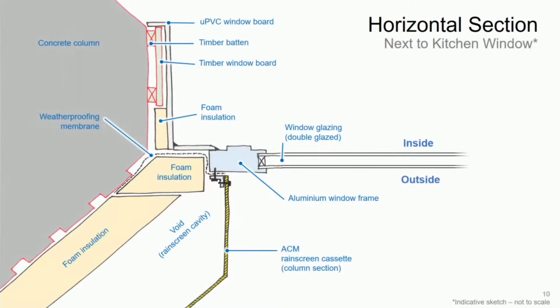On that basis, I developed this sketch of the materials, products, and geometry that exist at this location, and I noted that one potential route for fire spread to the cladding was through the side of the window and into the back of the cladding cavity. This could occur due to parts of the internal window surround and external cladding system being penetrated by the fire, essentially with the fire entering the cladding around the side of the window frame. In this case, the fire enters the cladding from the rear, but then finds a layer of polymer foam insulation facing a Reynobond PE ACM rain screen with a ventilated cavity in between them.